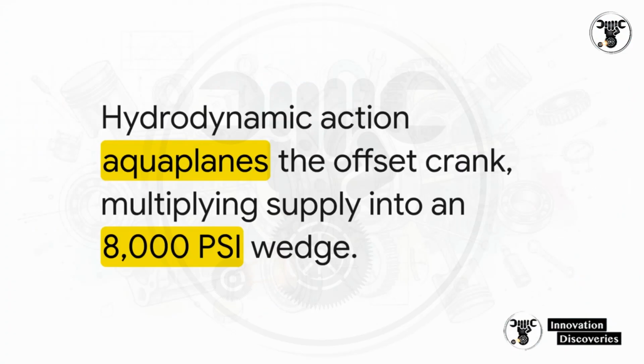Now, a lot of folks picture the engine's oil film as this uniform, perfectly even cushion surrounding the entire bearing. But actually, scratch that, that's not what happens at all. Under heavy load, the crankshaft journal is physically pushed off-center, and this offset or eccentricity creates an asymmetric, high-pressure convergent wedge pointing right in the direction of the load. This hydrodynamic action literally aquaplanes the massive steel crankshaft. It takes your standard 40 to 60 psi of oil supply pressure from the pump and dramatically multiplies it into a 3,000 to 8,000 psi wedge of completely impenetrable fluid.